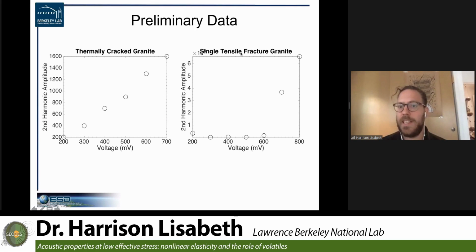For the single tensile fractured granite at low drive voltages, low strain, you don't get significant nonlinear behavior, and you reach some threshold where it starts to increase. And for a thermally cracked granite, so that means that you have distributed tiny microcracks all through it, cracked grain boundaries, you start to get nonlinear behavior at much lower strains. This is just some initial characterization to show the sort of studies that can be done to look at the unique or non-unique signatures of various things.